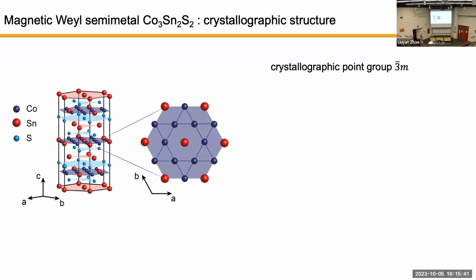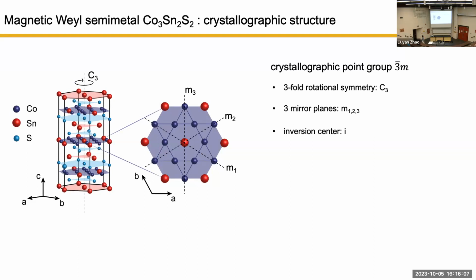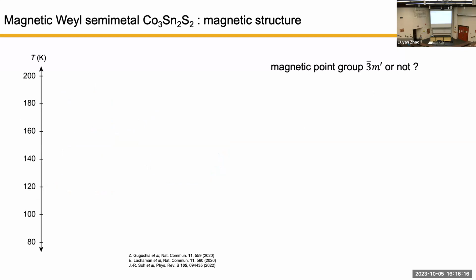And the focus of my work is trying to resolve the magnetic structure of it, because we said we have to use the magnetism to break time reversal symmetry so as to realize the Weyl semi-metal phase. So then it is natural that what type of magnetism it is breaking the time reversal symmetry matters. Yeah, so it's necessary for us to know the magnetism. Okay, cobalt tin sulfide essentially has the very same symmetry as what we showed before. It's a so-called bar 3M, 3-fold rotational symmetry, 3 mirrors, and inversion. So that's good. But what's puzzling in the literature is really what is the magnetic order in this particular compound. Even though people think it's a magnetic Weyl semi-metal, the magnetic order itself is actually debated.